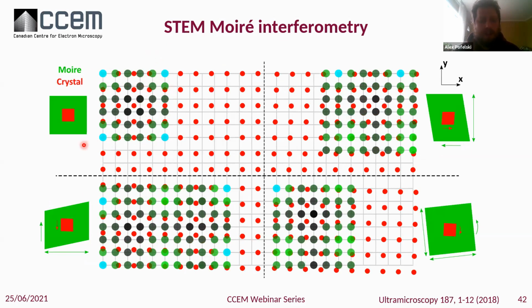This is the same setup that we had before. In blue, you have the corner of the maximum intensity. If we now consider a shear deformation, so a little bit of angle, we can see that we have some inner features coming in, and we don't have this nice squarish pattern that you have here. Only the two on the top are kept, but in all the bottom there is some intensity distribution with inner frequencies appearing. So definitely this intuitive approach is not sufficient.